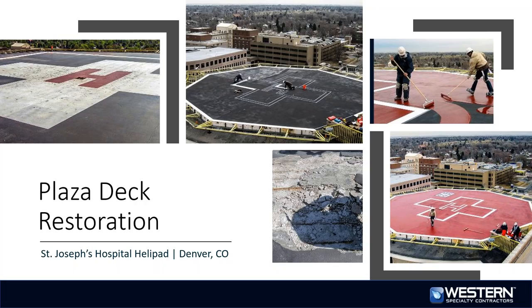But there was a lot of concrete deterioration in this deck. So the first thing we did was remove the old coating. We restored the concrete back to original condition. And then we recoated it with the methyl methacrylate coating, providing the necessary markings on the helipad as required by the hospital.